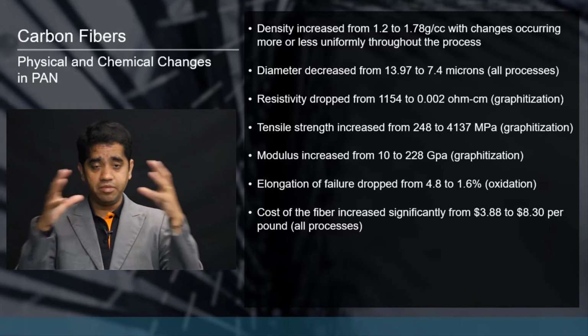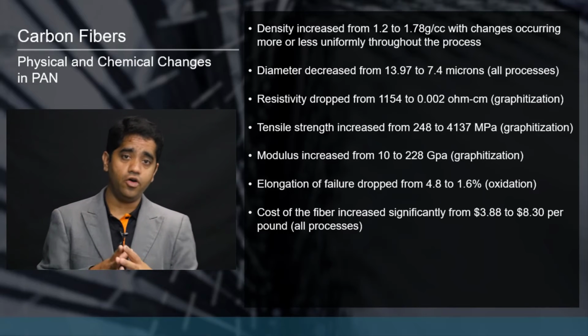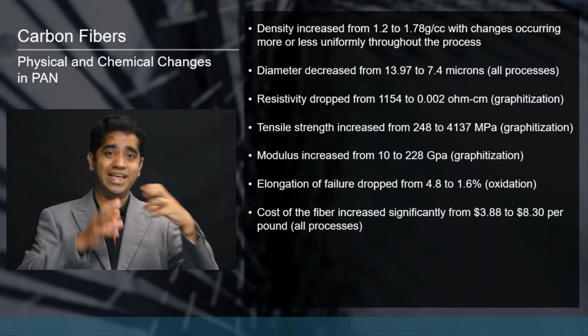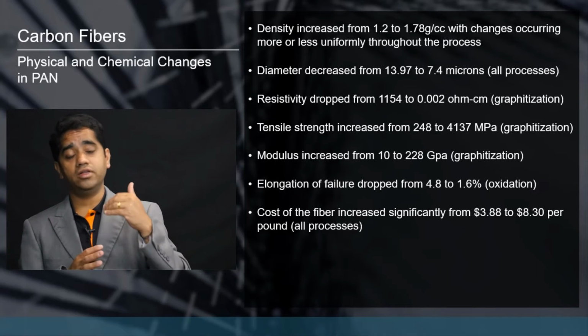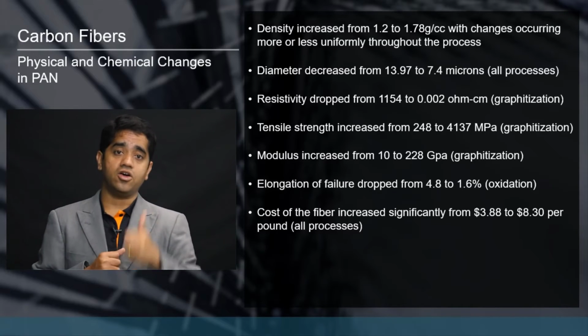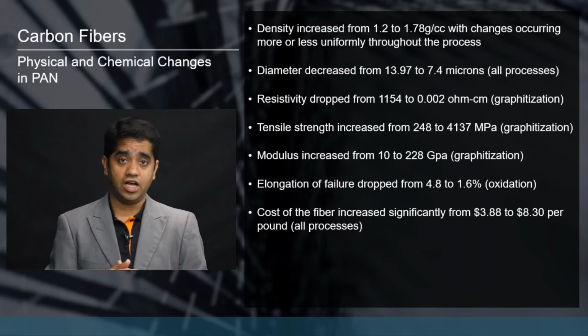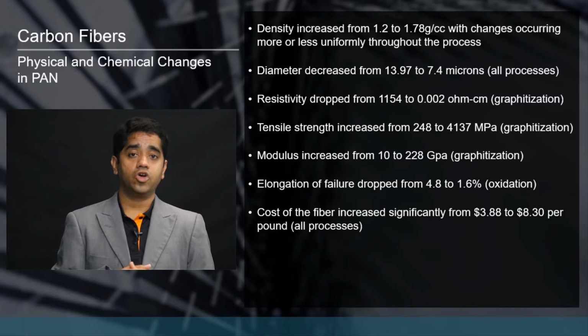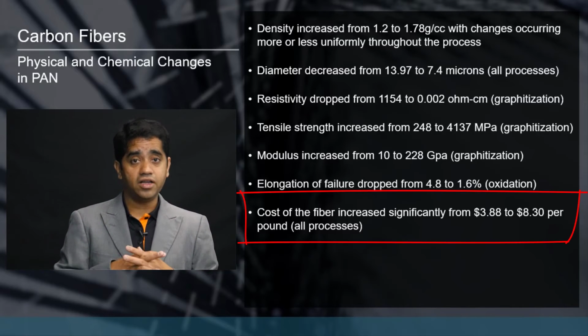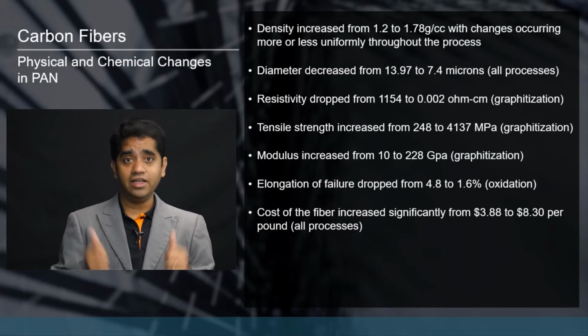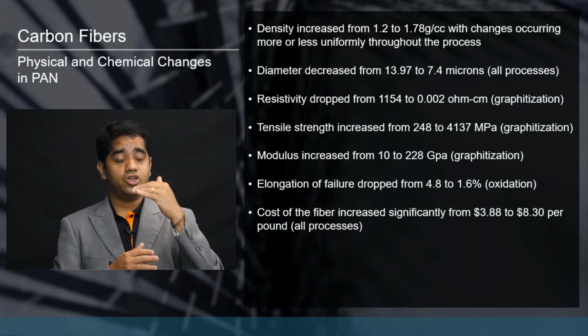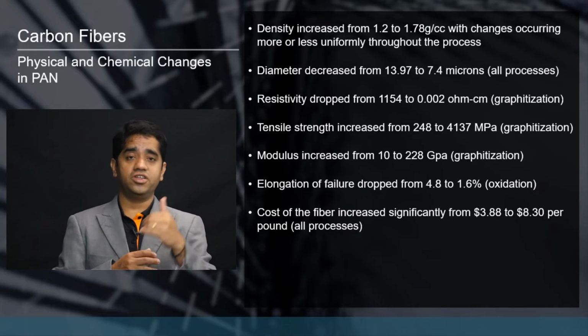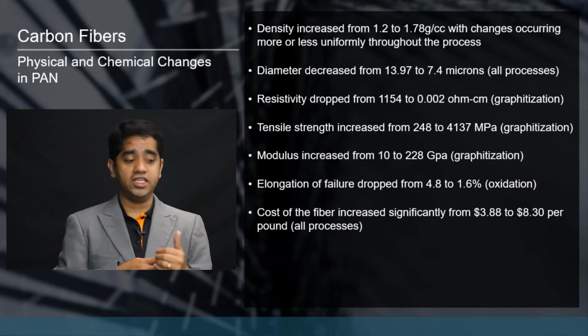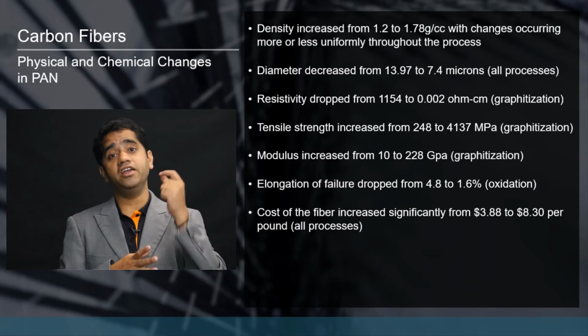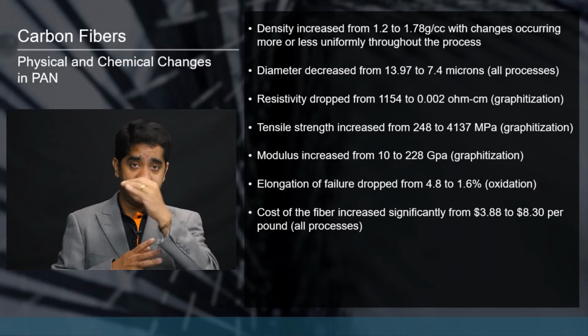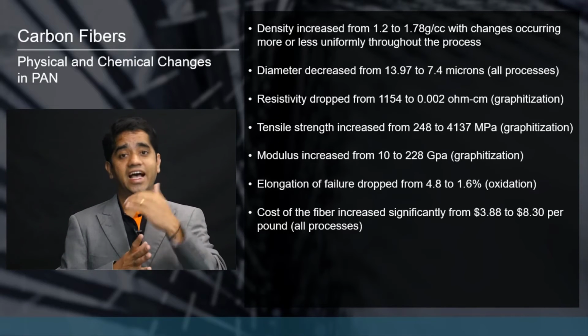So the higher the temperature you subject this to, and the longer you do it, you will remove more nitrogen atoms, more hydrogen atoms, and that will require more energy, and the cost goes up, and of course the cycle time also goes up, which definitely means that the cost of the fiber significantly increases. But the more pure the form of carbon you have, the higher the property will be. So if you remember, we talked about carbon fiber being standard modulus, intermediate modulus, and ultra high modulus. Between all these three, it is the amount of carbon content in the final fiber that is dictating the different types of properties as well as the cost associated.